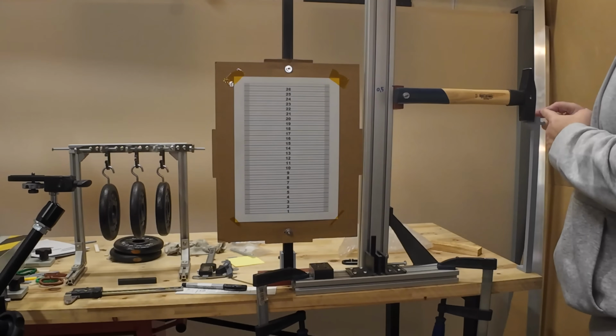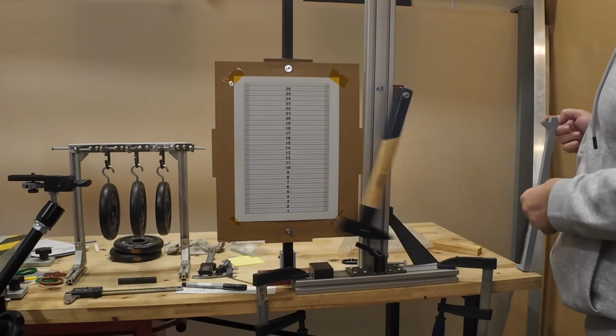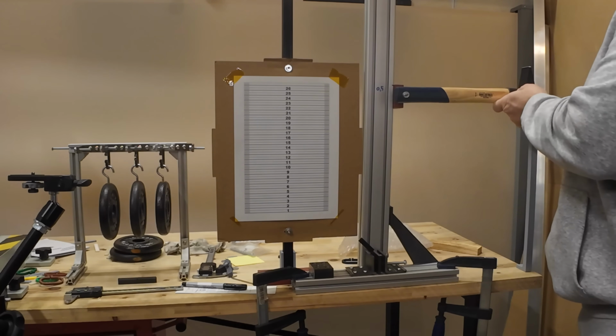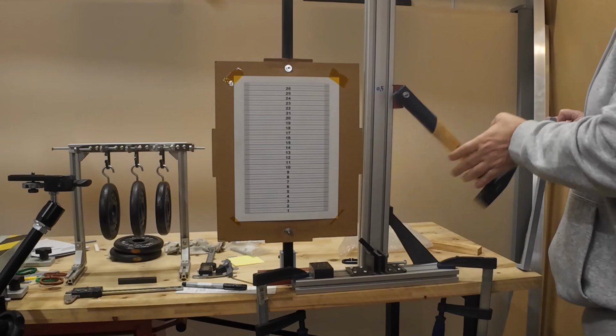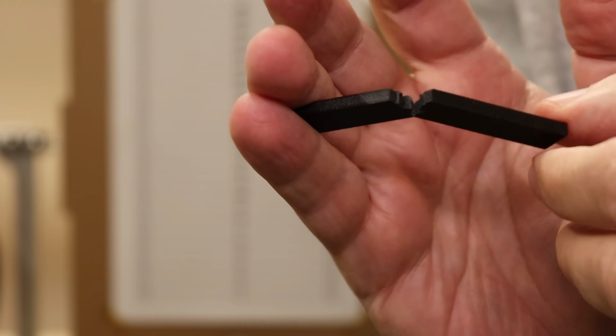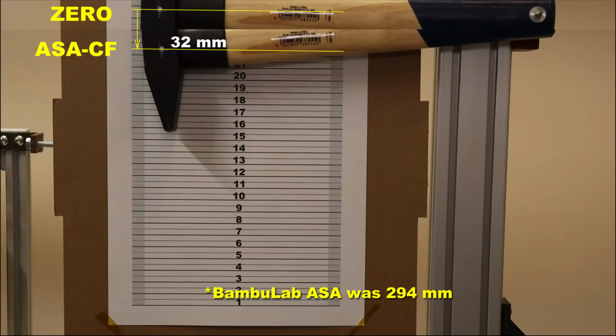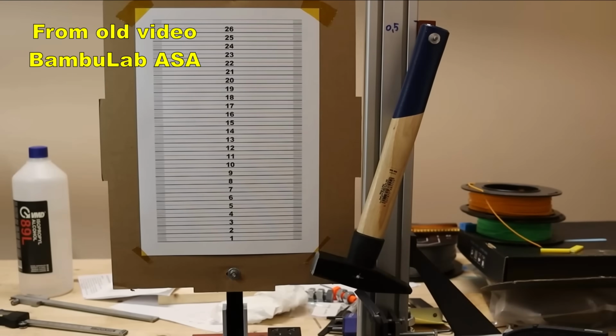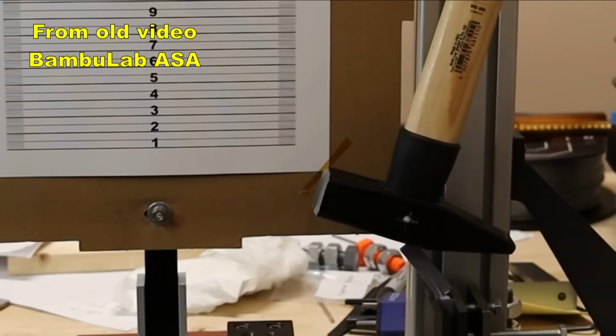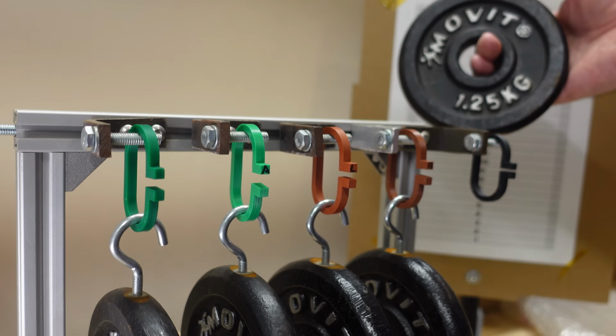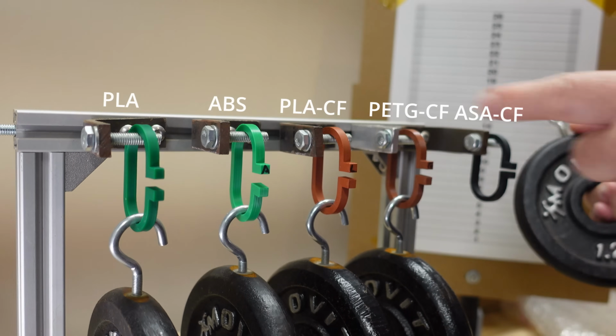Impact test with this half kilogram hammer, ASA-CF. 0 position. And now let's check the numbers. Compared to the average PLA or PETG material, the ASA-CF is tougher, but compared to the non-reinforced ASA material, this is much more brittle. The creep tests the deformation under the constant load, and I have several tests in the progress with different materials, so it will be a good reference.